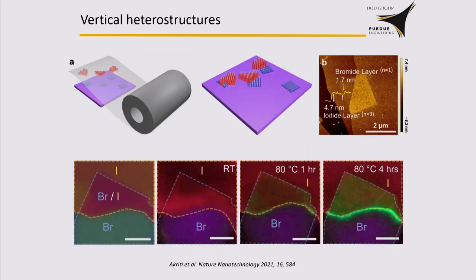And for the vertical stacking, the fabrication is very easy, straightforward. There's nothing surprising. But indeed, once we put them together, lots of interesting physical properties show up. For example, in this work, we discovered a unique layer-by-layer interdiffusion process between the iodine and the bromine ions across this interface. Due to the limitation of time, I won't be able to talk about the details, but if you are interested in solid-state diffusion, please take a look at this paper.